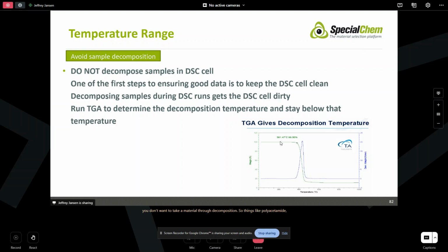So things like polyacetal, for example, you don't necessarily want to take that above 275, something like that. PVC is a great example. I was working with a client who came to me and said that their DSC was giving them problems. What I came to realize was that they were taking PVC, heating it through decomposition, which generates HCl, and that hydrogen chloride just kind of chewed up the inside of their cell, and they had to replace the whole cell. So again, one way you can avoid that is to run TGA first and understand where the breakdown of that material is, whether that be decomposing to dangerous species or simply giving off stuff that's going to contaminate your cell. TGA can be a big help with that.